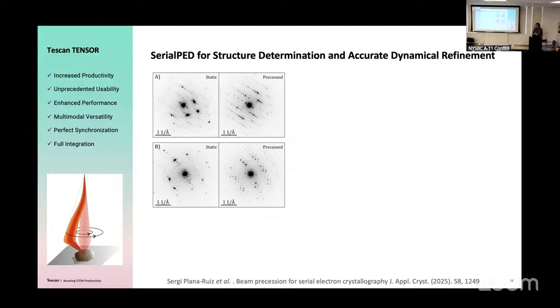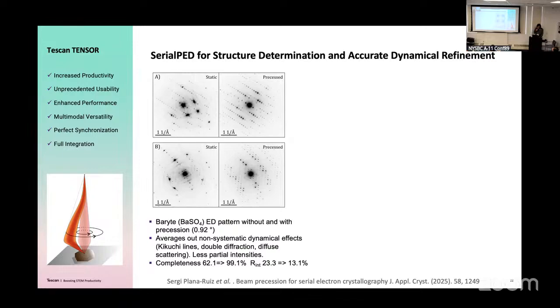And then serial electron diffraction is becoming more and more popular, but it also has limitations. With static images you have dynamical effects, and it's difficult to index because you have high partiality. If you precess the beam, you see it on the right side, you get full reflections, and a lot of the dynamical artifacts go away, as shown here for this example.